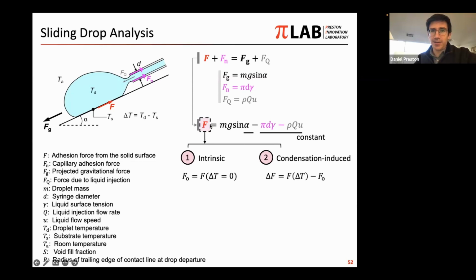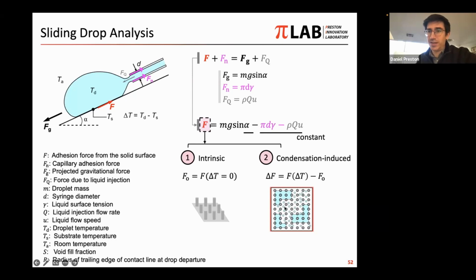And then we can try to characterize this adhesion force F in terms of two different contributions. One is an intrinsic or innate, just the same adhesion force that you would get on the super hydrophobic surface at room temperature with water. And then one of them is due to this condensation inside the structures, and that can be referred to as delta F that gets added on there. And so those are sort of shown schematically in these two pictures. F naught is just what you'd expect for the super hydrophobic surface at room temperature, and then we might have some evaporation and recondensation inside the structures that gives us a delta F, more adhesion.